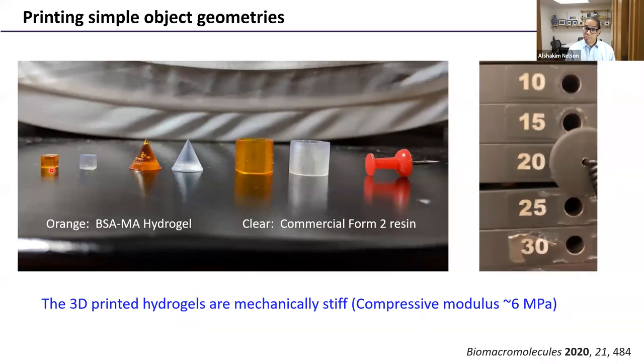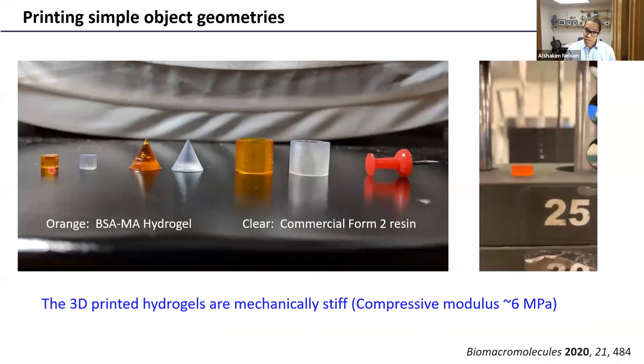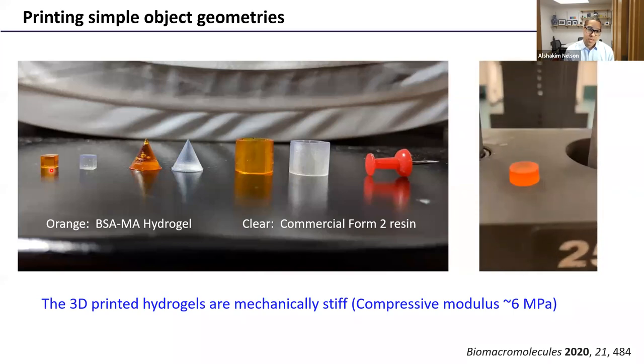And he took me quite literally because he went to the gym and put weights on this printed puck, but you can see here that there's no sign of mechanical damage after putting this 20 pounds of weight on the hydrogel. And so in fact, these do have a compressive modulus that approaches cartilage.